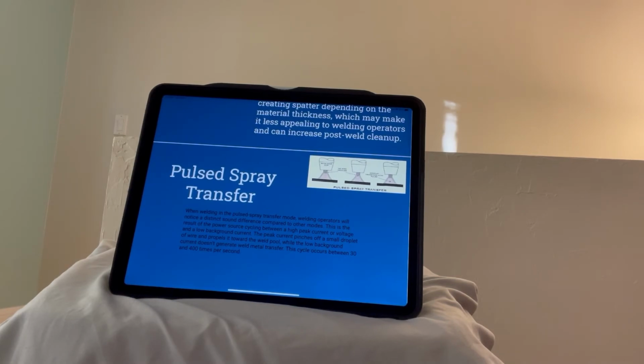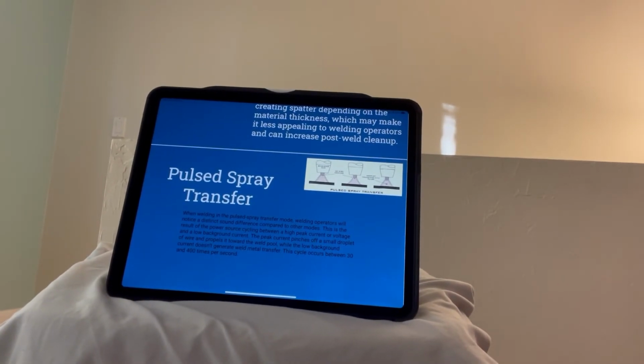And pulsed spray transfer. Operators will notice a distinct sound difference compared to other modes. This is a result of the power source cycling between a high peak current or voltage and a low background current. The peak current pinches off a small droplet of wire and propels it towards the weld pool. The background current doesn't generate weld metal transfer. This cycle occurs between 30 and 400 times per second.